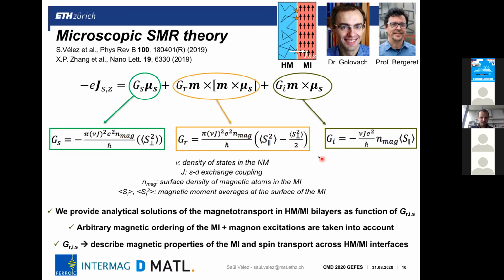Importantly, these equations allow us to explain the spin transport properties across interfaces with systems that don't exhibit, or do exhibit, any type of magnetic ordering, for instance antiferromagnets or even paramagnets. We also developed analytical equations taking into account these contributions. And also important is this term here: for instance, at high temperatures, or across a ferromagnetic transition, you could excite a lot of magnons in the system, and this was not taken into account initially, although now it's quite clear that the excitation of magnons in the magnetic insulator also contributes to the magnetoresistance in the heavy metal magnetic insulator bilayers.